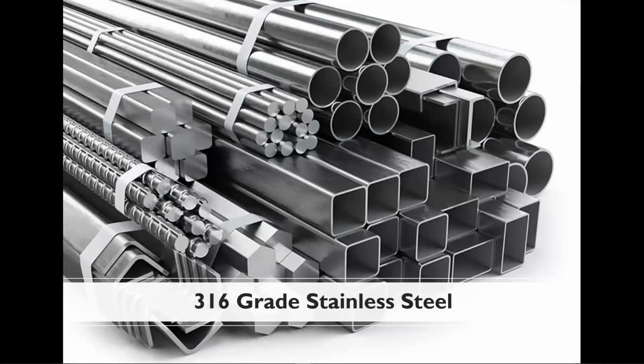And specifically for the biomedical application, one benefit is that, interestingly, its as-built design is used in medical orthopedic implants, as the porosity of the additively manufactured metal of a similar composition resembles the porosity of bone. It's aiming to replicate that in its design, kind of increasing the osseointegration there.